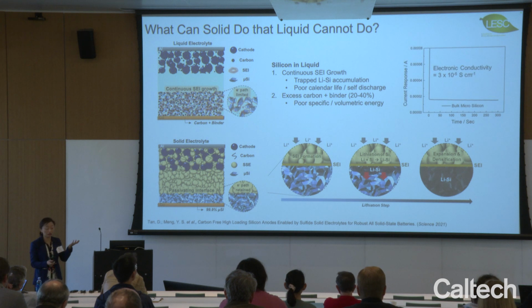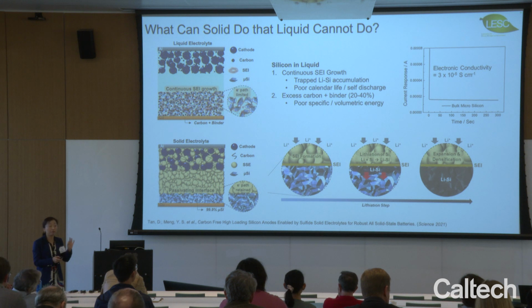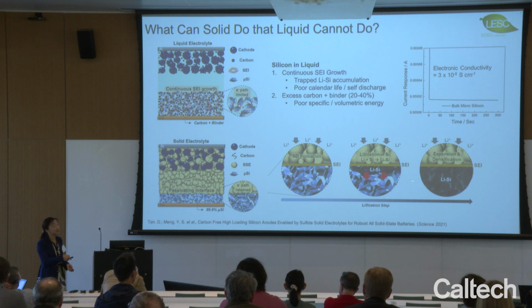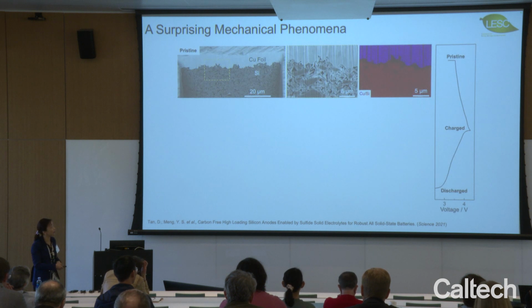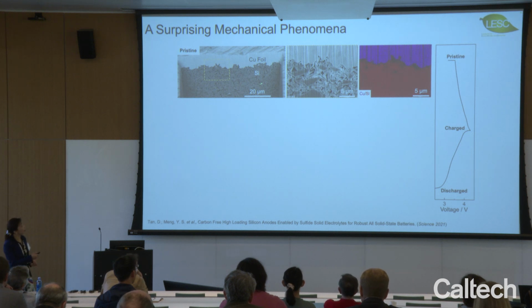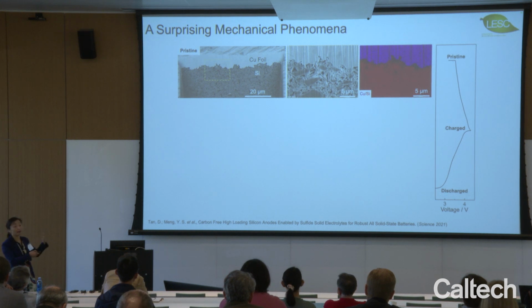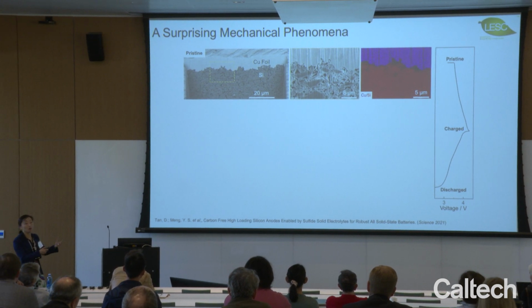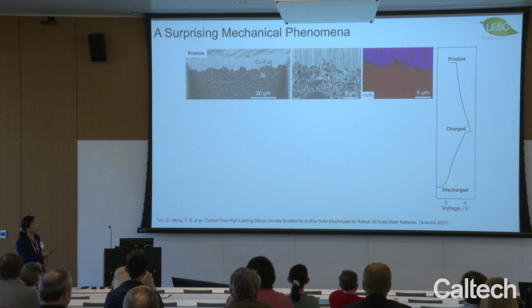And one important requirement for this silicon to work is that you want to use cheap metallurgical grade silicon. We don't want the fancy ones where the surface is usually covered by a lot of oxygen, so the electrical conductivity will be impacted, because the concept will only work if you have a true mixed conductor where the electron and the ion will both be conducting through this process. So in the cell, when you make the silicon, this is completely random. You see the particle size varies a lot. It's something we buy from Sigma Aldrich at extremely low cost.